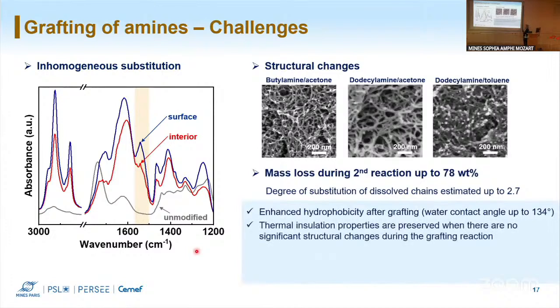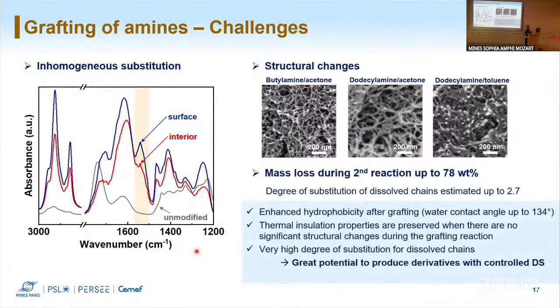We could preserve the thermal conductivity of the structure if we had preservation of the network during the reaction. Then we could achieve a very high degree of substitution, but only for the dissolved chains. And it opens a very big door to produce derivatives of pectin with controlled degree of substitution.